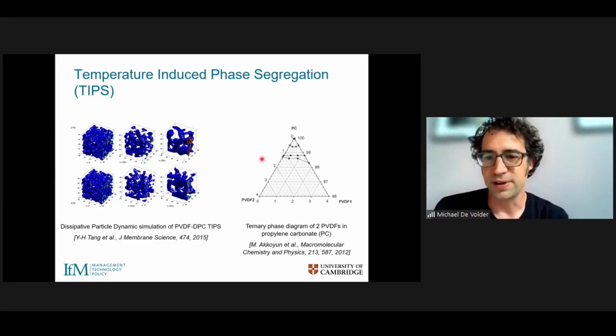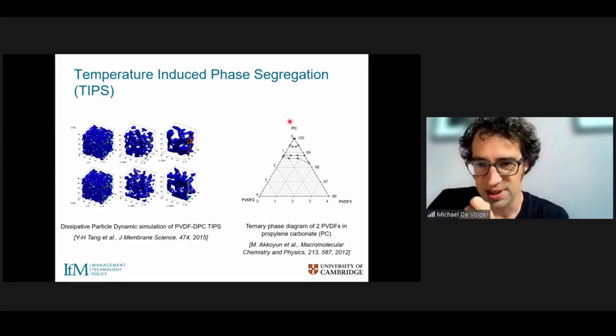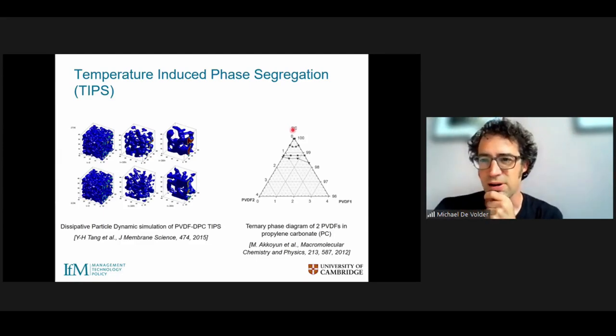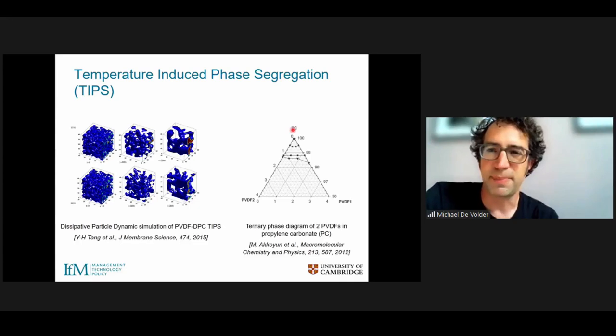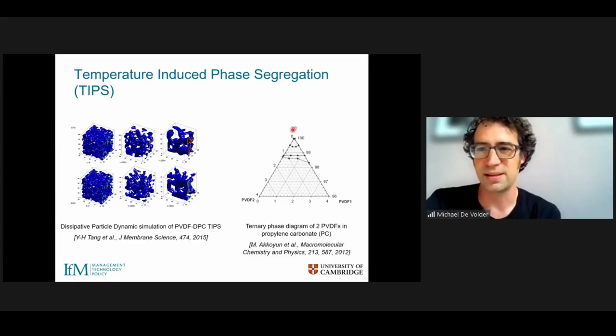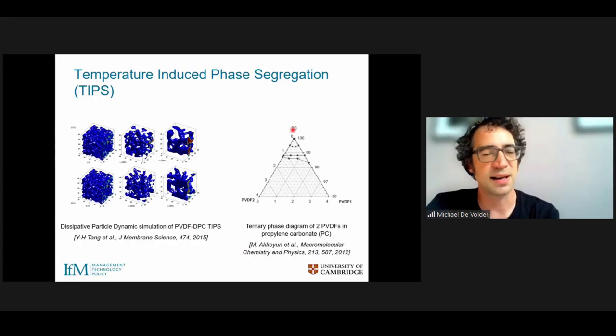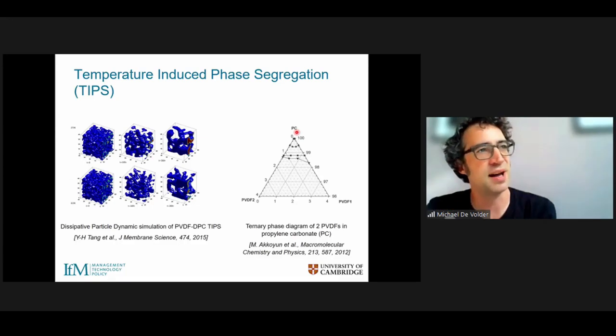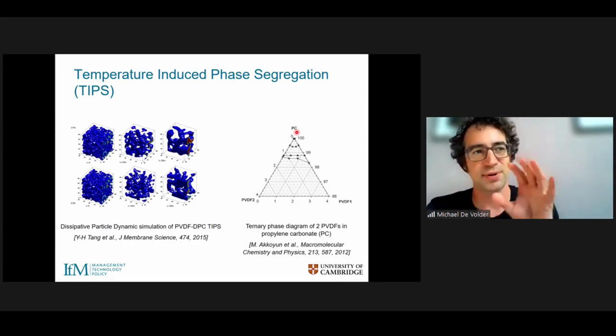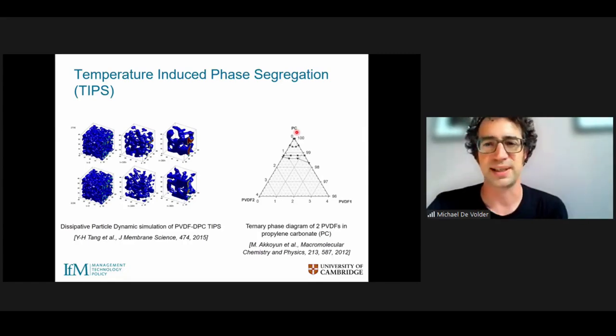The other thing we found interesting is that these phase segregation processes for PVDF can be done with solvents such as PC, which stands for propylene carbonate. And that's interesting for batteries because propylene carbonate is oftentimes used as a solvent in the electrolyte of the battery. So lithium salts are oftentimes dissolved in PC, propylene carbonate. And then these salts in solution form the electrolyte that helps transporting lithium ions from the anode to the cathode.